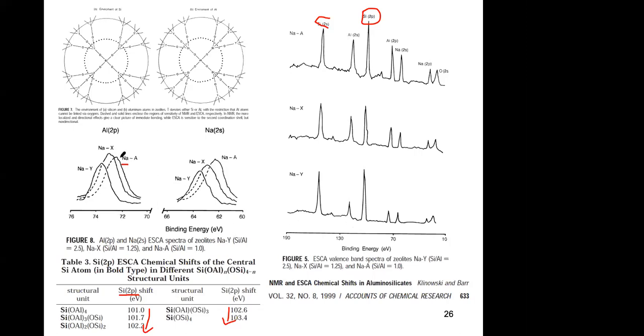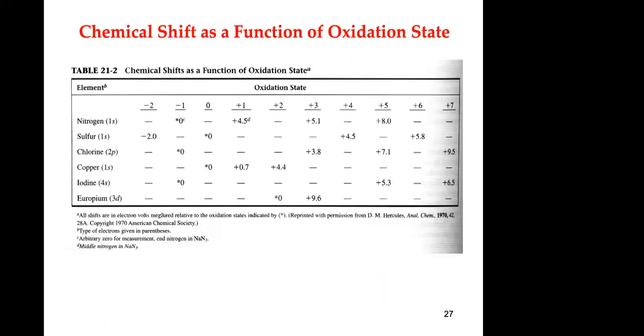And here you can see the shift in the aluminum 2p and sodium 2s. So the silicon is the one that changes the most, but sodium 2s and aluminum 2p also change the binding energy. So that's a very useful way to look at structure, chemical shift and chemical structure.